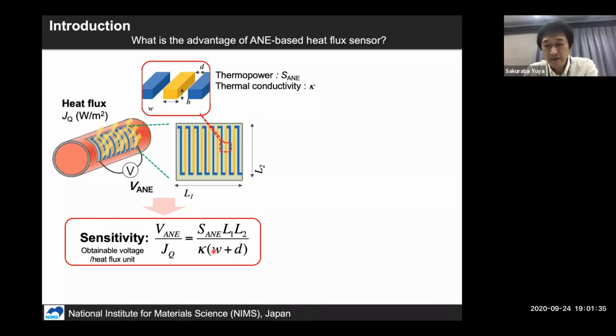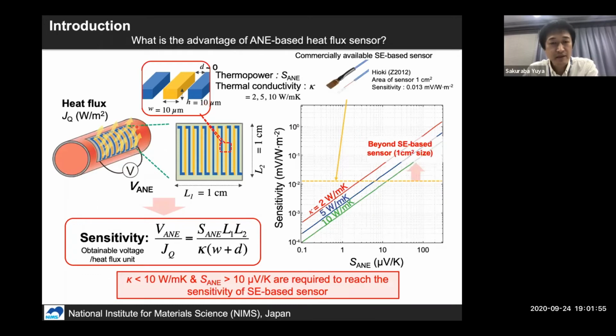To evaluate the specific value here, we put the sensor size at 1 centimeter, and the width and height of the magnetic material at 10 micrometers. In this condition, we calculated the sensitivity of the heat flux sensor as a function of the thermopower of the anomalous Nernst effect. Because the sensitivity is inversely proportional to the thermal conductivity, we put three different thermal conductivities for this simulation. And when the thermal conductivity is 10 watt per meter Kelvin, as you can see, in order to overcome the sensitivity of the current commercially available Seebeck heat flux sensor, we have to realize over 10 microvolt per Kelvin.